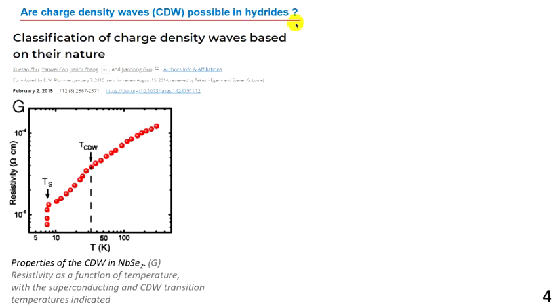Okay, to answer this question, let's look at the temperature dependence of electrical resistance in different compounds. In layered, for example, layered niobium diselenide. And we can see on this plot that before the superconducting transition in this material, we really can observe in the temperature dependence of resistance a similar wave, a similar upturn feature as we observed in hydrides.